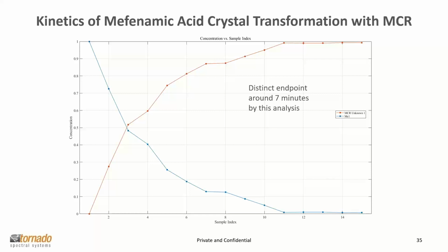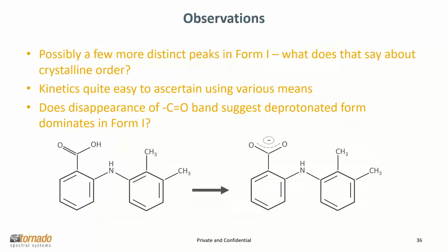And if we look at that a little more carefully, we see, compared to the other analyses that we did, perhaps a little bit more distinct indication of the endpoint in the data based on what we see through the multivariate curve resolution. So by this, it looks like the endpoint was reached maybe a little bit sooner than the 10 minutes that was allowed, maybe even up to 7 to 8 minutes into the analysis is when we see a consistent level of form 1 over form 2.